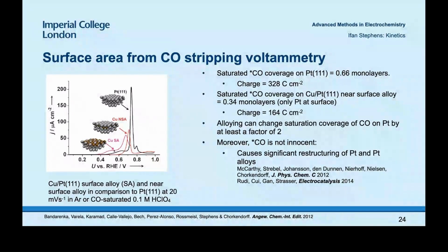We particularly looked at this kind of copper near-surface alloy, where you have a pure platinum surface, but with copper in the second surface layer. We can actually change the saturation coverage of CO on platinum by a factor of 2. Also, another thing to bear in mind is that often when you add CO to a platinum surface, it causes restructuring of the surface, and that can also cause some artifacts in the measurement. So just by doing the CO stripping measurement, you can actually induce changes to the catalyst surface.